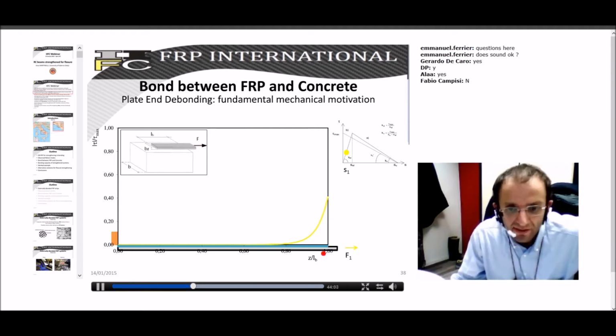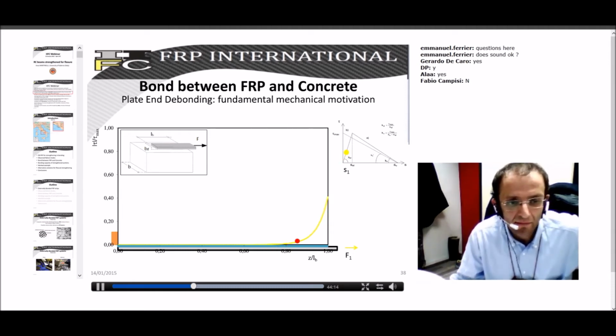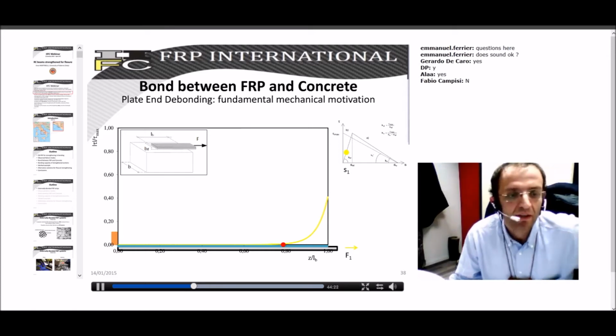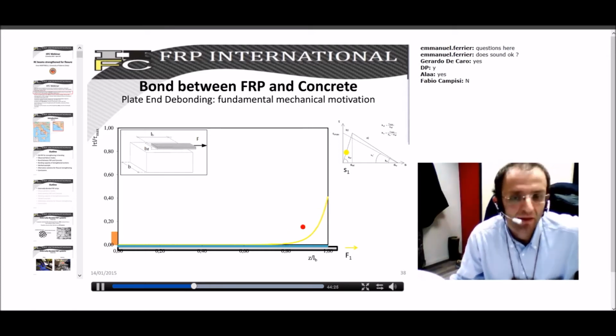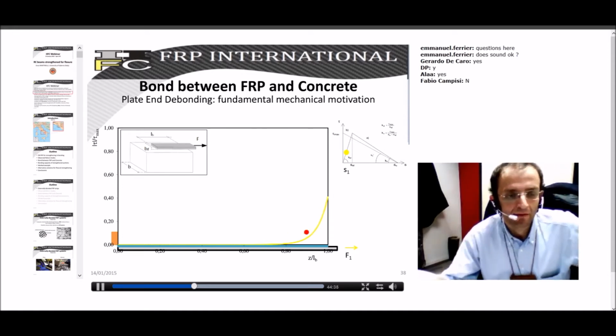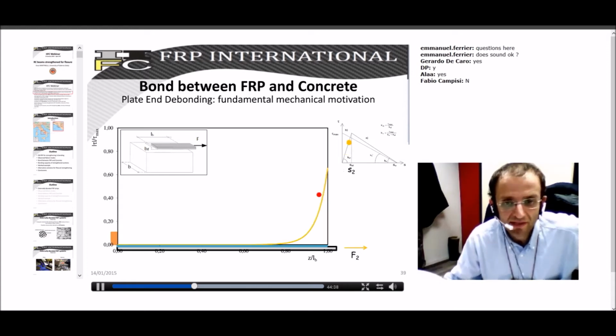So S1, you can solve the equations I reported before. We are in the elastic range, so we have an exponential solution. So these are the tau. I remind you that this curve is as sharp as alpha is high. So if you have a high alpha, which means a stiff interface, you have a very sharp distribution, a very high gradient of this tau. Otherwise, you have a more uniform distribution. If you increase the displacement, but you are still in the elastic range, you still have